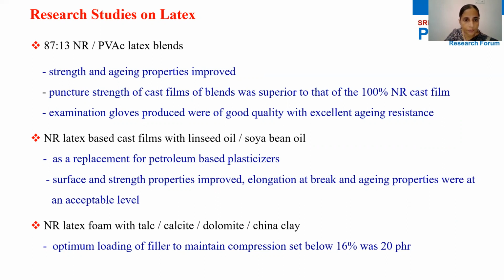Natural rubber latex-based cast films were produced with natural oils, linseed oil as well as soybean oil. This research was carried out to see whether petroleum-based plasticizers, such as white oil used in natural rubber latex-based products, can be replaced by natural oils. Surface and strength properties improved, elongation at break and aging properties were at an acceptable level. The cast film produced out of linseed oil exhibited a glossy surface finish.